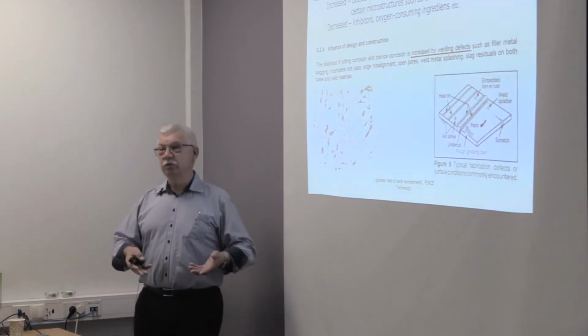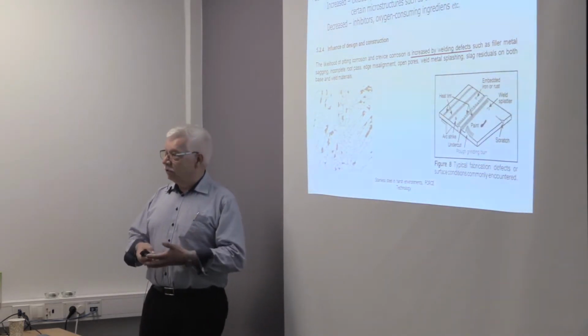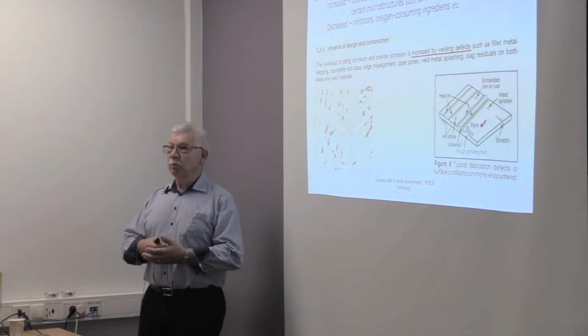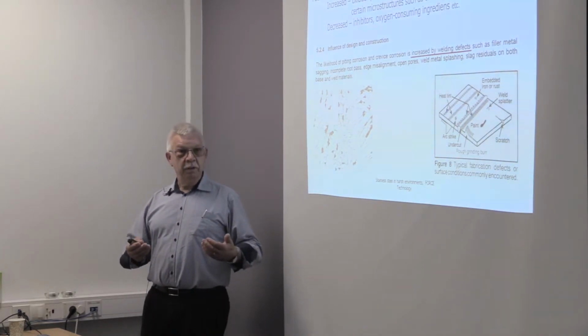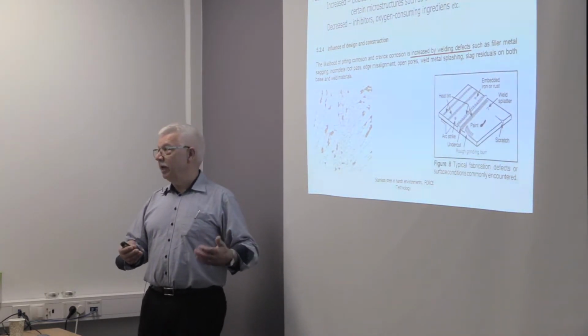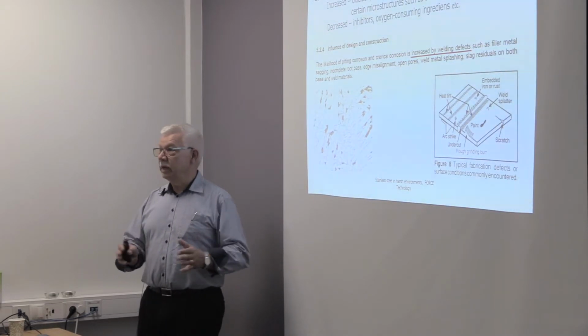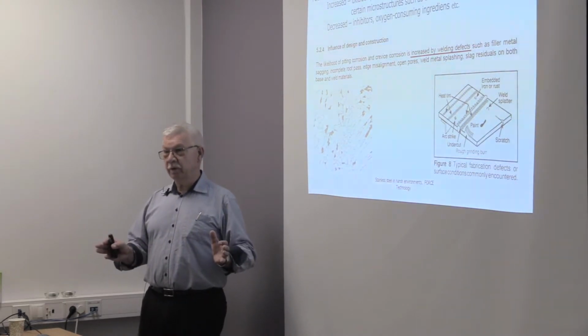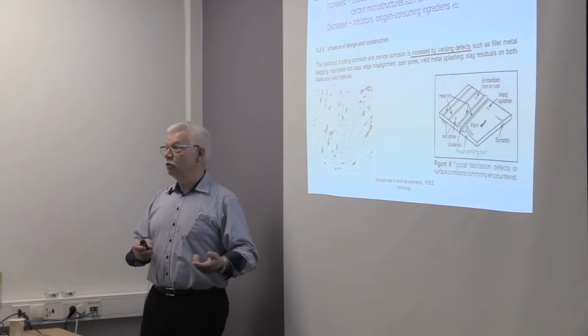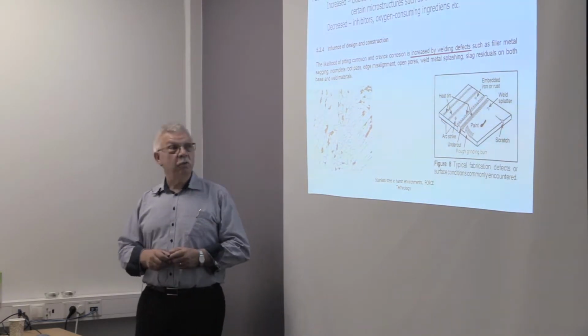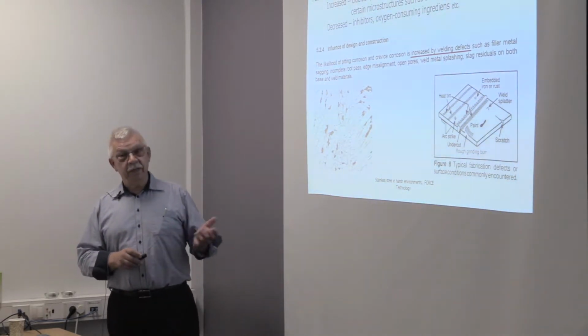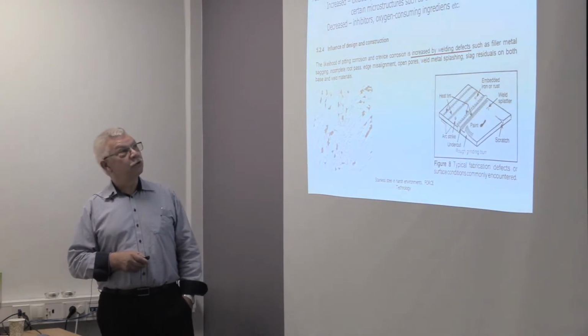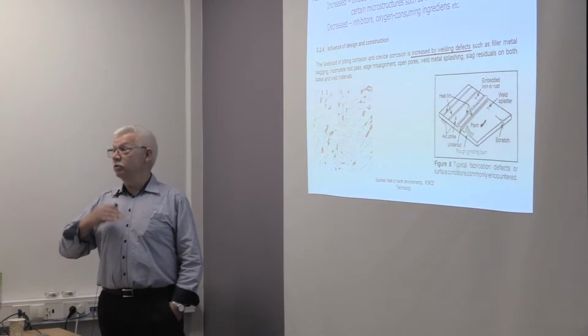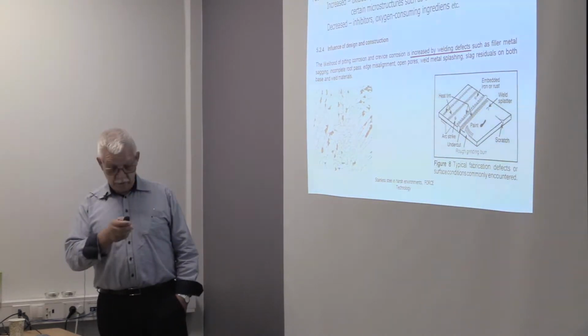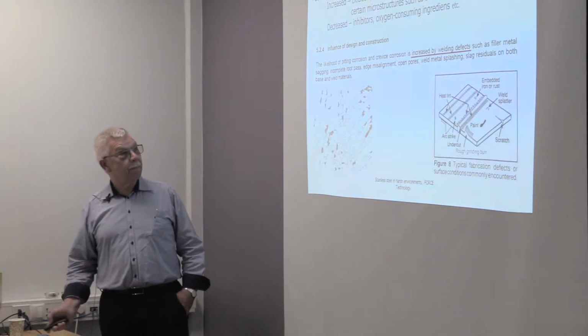And I think you know that if you have a central heating system in your house, when you put on new water, the oxygen will go in and it will be consumed by the steel surfaces in there. And once consumed, there's no oxygen and there's no corrosion in this system until you put on new water. So anything in the media which will consume oxygen will lower the corrosion resistance below what you predict from the diagrams that I have shown you before.